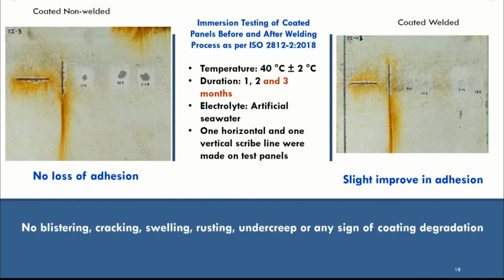Now we know there is a layer, a passive layer. However, we have understood from the two parts that this first layer is susceptible to any pitting or under-crevice corrosion. However, we have found from linear polarization that after 2 weeks, it takes some time for it to come back to normal. So we know there is a problem. We know there is a change in the morphology of the coating. We wanted to know, if this happened and we used it in the field, how this coating is going to